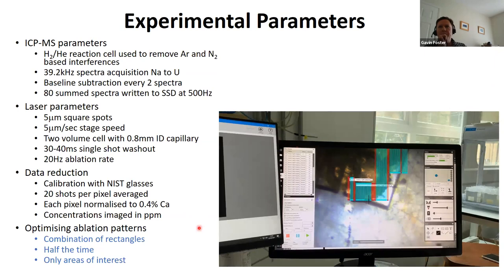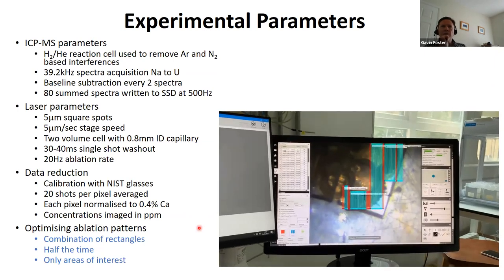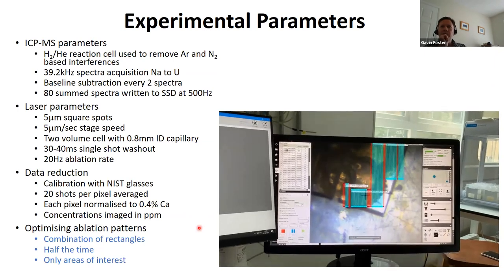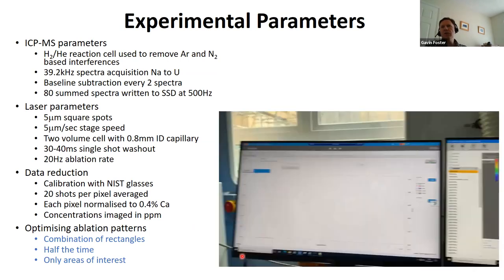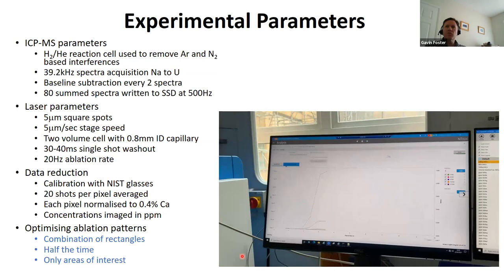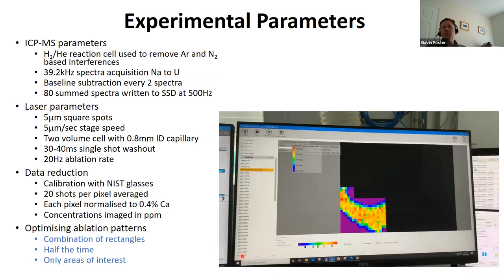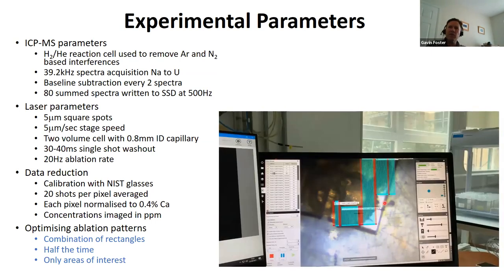So Phil and Lucas came up with a method of segmented analysis where you get a combination of rectangles, and that is then constructed together by the Vitesse to give you a sort of irregular laser ablation image. So you see that the rectangles are drawn on here, and those are then combined together. That means we only use about half the time, and we're really focusing in on the area of interest.